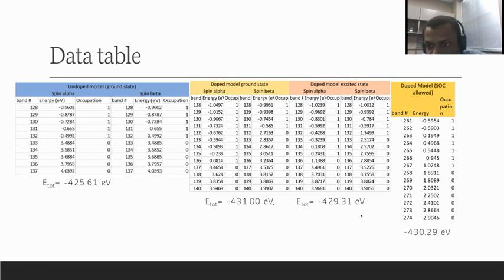And in the last table, these are the band numbers, energies and occupations for the non-collinear spin DFT. So that one accounts for the spin orbit coupling. It is allowed in this case. And here the occupations, instead of being separated into alpha and beta orbitals, are just whether they're present or not present.